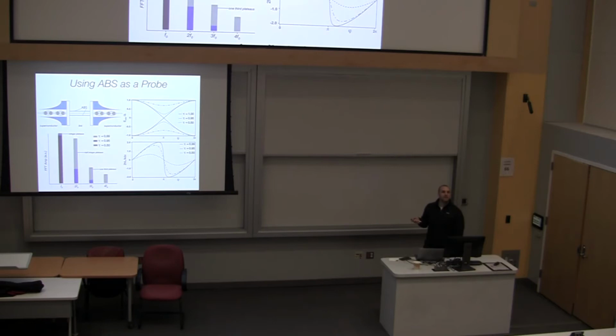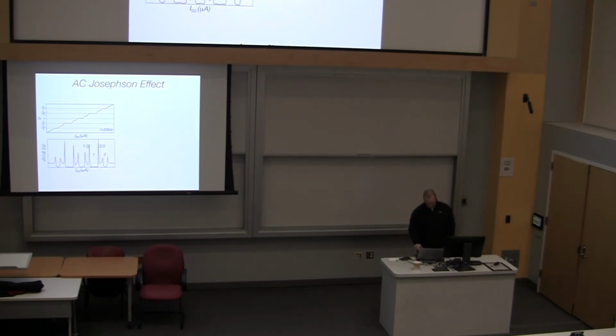they contribute very little to the supercurrent, because as T goes down, the amplitude of the supercurrent goes down. In addition, they don't contribute anything to the skewness of my current phase relationship. So if I had things on the surface, even in the presence of a large bulk background, that were highly transmitting, I would get a stronger contribution to the supercurrent. And also, if I measured the AC Josephson effect, I would be able to pick out their skewness by seeing these subharmonic steps.